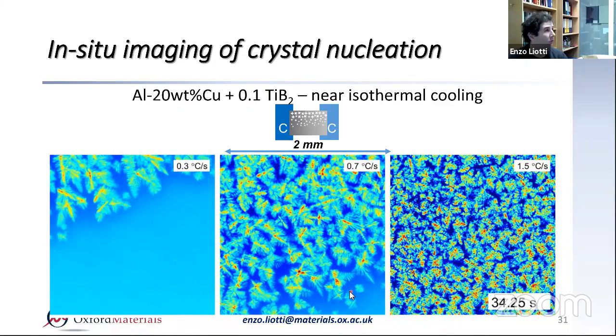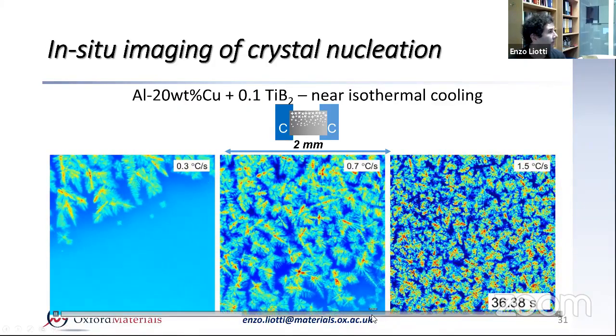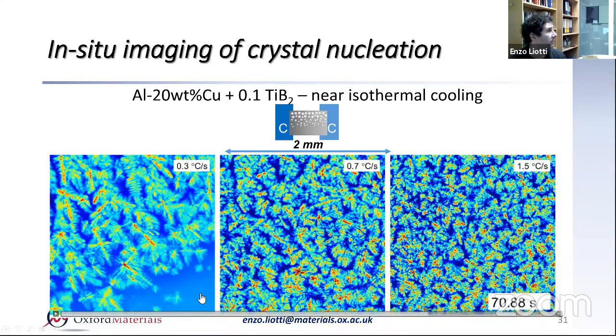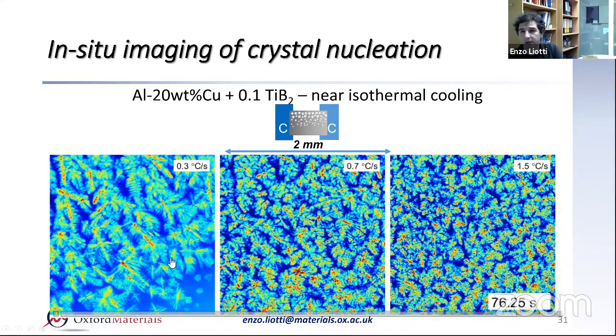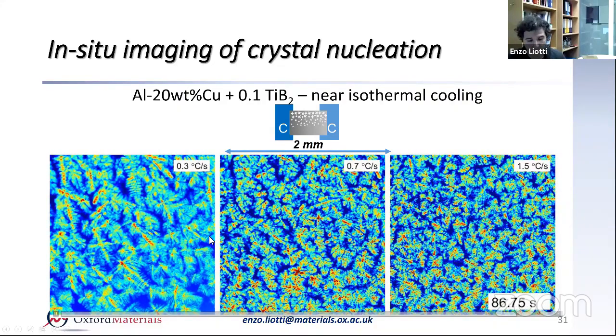And in fact, if we go towards the end of the video, which is somewhere here, you can see that the grain size, even by eye without any measurement, is much smaller on the right than on the left. And that's kind of known: if you increase the cooling rate, you increase the nucleation rate, and you get a smaller grain size. So far so good.